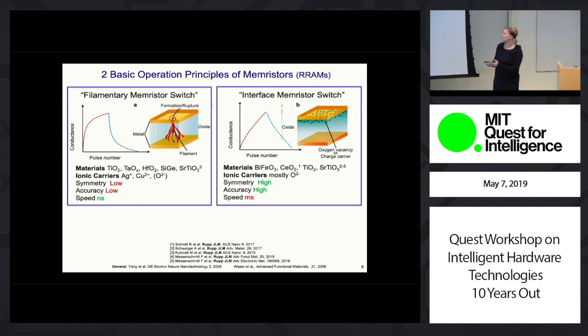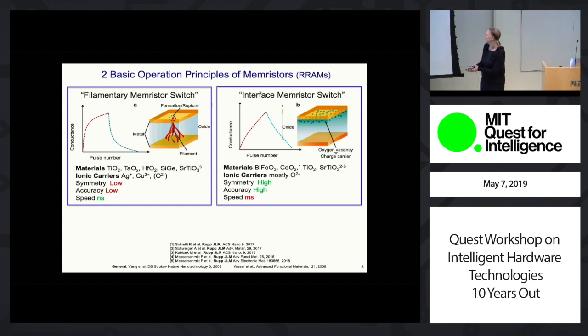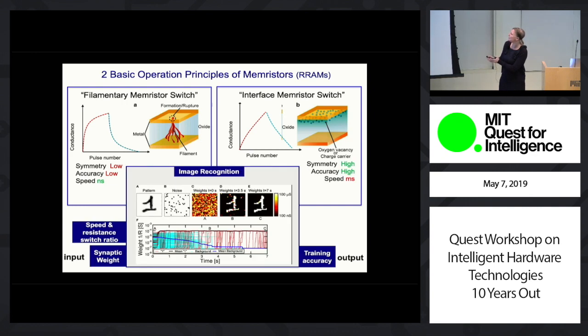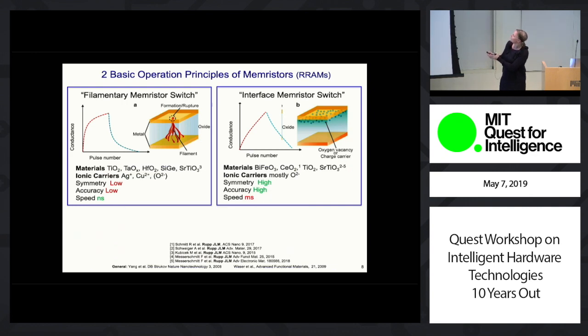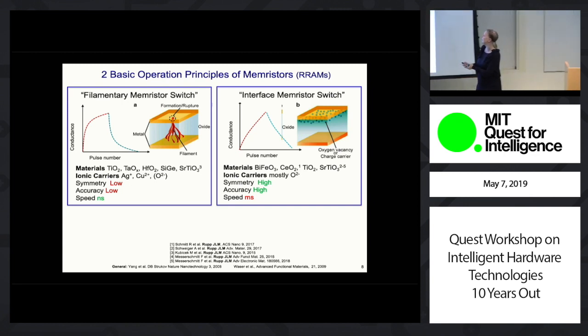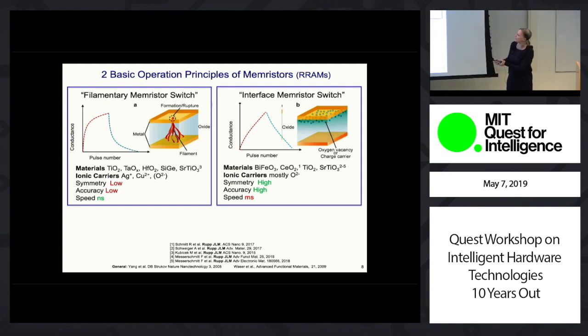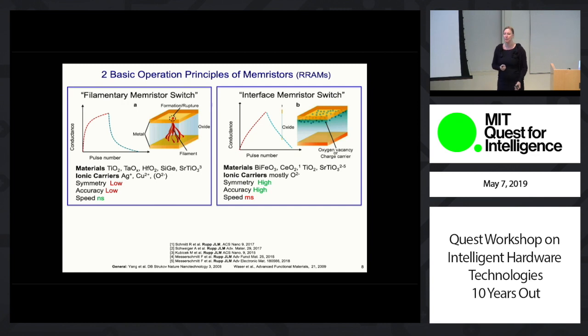The other type of memristor that has been published in the literature, and I want to highlight here the work of Yang and Strukov and others from HP and Rainer Waser, where you can read much more about it, is the interface memristor. In the interface memristor, you have defects that you accumulate at one interface, and when you apply the bias in the reverse direction, they shift back to the other side. You're shuffling back and forth mostly oxygen ions over defects in the electrolyte material. The consequence is that the symmetry is quite high, so you don't have such an abrupt change like in a cation migration mechanism. The accuracy is high, but the speed is relatively low.